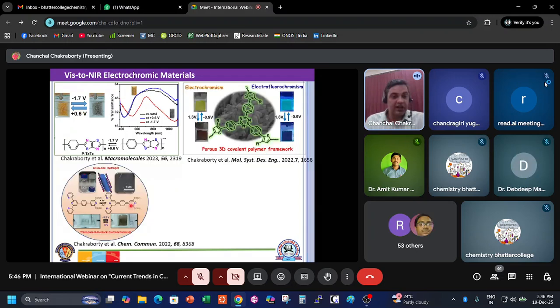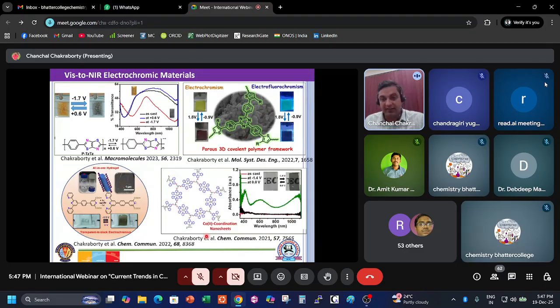Basically, for electrochromism you need a film, but not all materials can make a good film, especially conjugated polymers or the porous 3D covalent polymeric framework, if they are sparingly soluble in the solvents. So in that case you can prepare an all-in-one gel, and we have used that. We used a terpyridine-containing moiety and produced a transparent to blackish color electrochromism in that gel. Also we developed a metallo-supramolecular polymer with cobalt, and that can show a color change from transparent to blackish color basically, and that can absorb in that NIR zone.